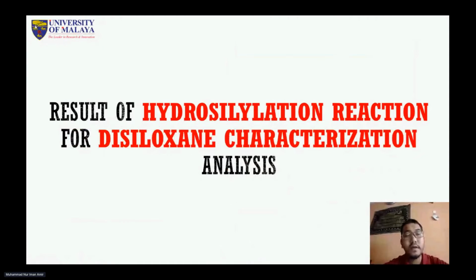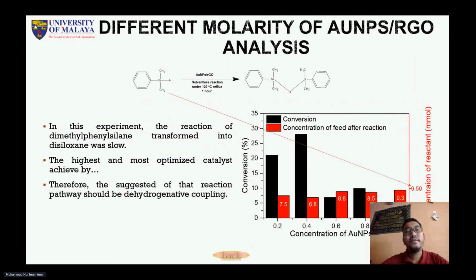Lastly, we want to explain the result of the hydrosilylation reaction here. What we can say here is that the reaction with different molarity of catalyst is confirmed by the substrate used being transformed into the final product slowly within 1 hour, so the highest and most optimized catalyst was achieved by the sample of 0.4 millimolar concentration of gold nanoparticles. Therefore, we suggest the reaction pathway should be dehydrogenative coupling.